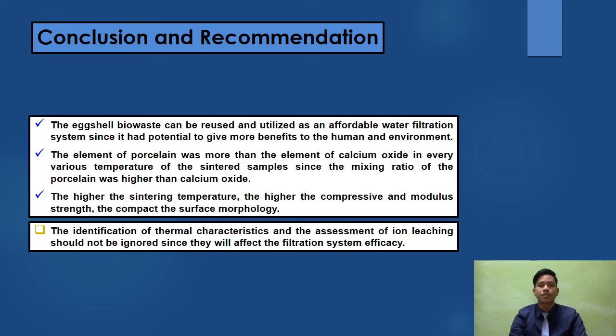The element of porcelain was more than the element of calcium oxide at every temperature of the sintered samples since the mixing ratio of the porcelain was higher than calcium oxide. The higher the sintering temperature, the higher the compressive and flexural strength, and the more compact the surface morphology. Lastly, for the recommendation of the study, the identification of thermal characteristics and the assessment of ion leaching should not be ignored, since they will affect the filtration system efficacy.